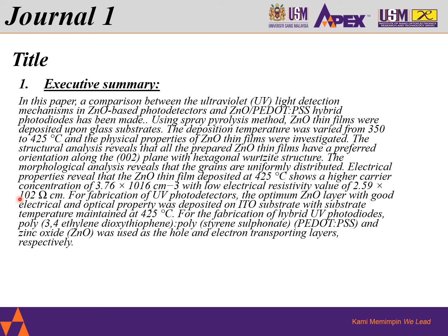films were investigated. The structural analysis reveals that all the prepared zinc oxide thin films have a preferred orientation along the 002 plane with hexagonal wurtzite structure. The morphological analysis reveals that the grains are uniformly distributed. Electrical properties reveal that the zinc oxide thin film deposited at 425 degrees Celsius shows a higher carrier concentration of 3.76 x 10^16 per cubic centimeter with a low electrical resistivity value of 2.59 x 10^2 ohm per centimeter.